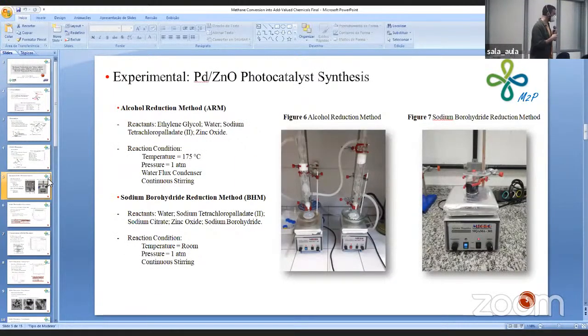And as experimental, we use two different methods for the photocatalyst synthesis. The alcohol reduction method, represented in figure 6, and the sodium borohydride reduction method, represented in figure 7. In both methods, we use Sigma Aldrich nanosized zinc oxide as the semiconductor, and a solution of tetrachloropalladate as a palladium precursor. Both methods were carried out in an aqueous system, and the solid content was separated by centrifugation, washed several times, dried in the oven, and ground to a powdery appearance.